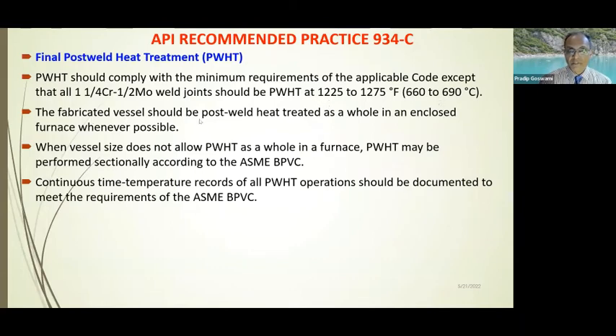And for the fabricated vessel, you need to do post-weld heat treatment as a whole in an enclosed furnace wherever possible. Sometimes it may happen the furnace is not long or big enough to allow post-weld heat treatment of the entire vessel in a single go. But in that case, sectional post-weld heat treatment is allowed, or may be performed, as per ASME Section 8 Div 1 or Div 2, that is the fabrication code which is adopted for design and construction.